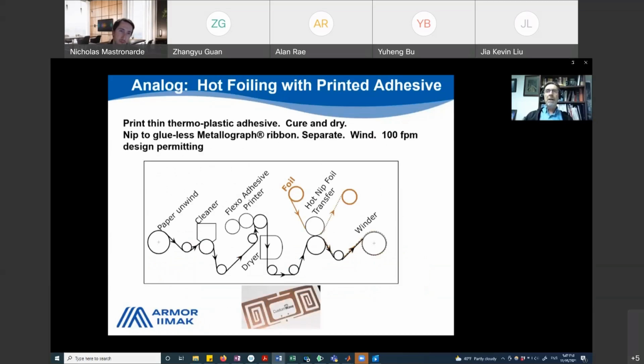There's several well-established methods for metallic foil transfer. We have seen successful demonstrations with two of these methods using metallograph. The first involves printing an adhesive in a pattern of an antenna or other electronic circuit onto a substrate, and then using that adhesive to adhere to and transfer off the metal layer from the ribbon to itself in an image-wise fashion. Adhesives for RFID antenna production have been successfully printed using flexo technologies, like the example shown on the slide below. However, other methods, such as inkjet printing, may also be successfully used to add a digital capability to printing the adhesive.